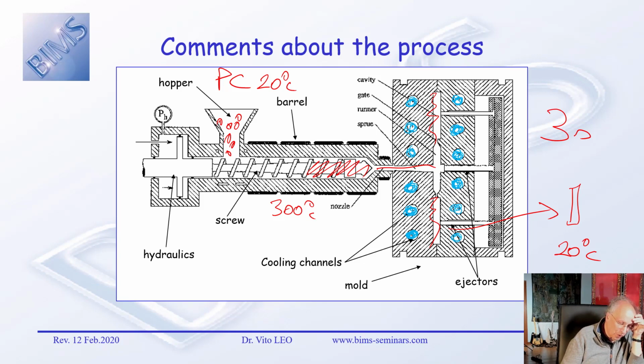Why? Well, because the cooling time or the cycle time can be estimated by taking roughly 3 times the square of the thickness. If you put the thickness in millimeters, you end up with your time in seconds.